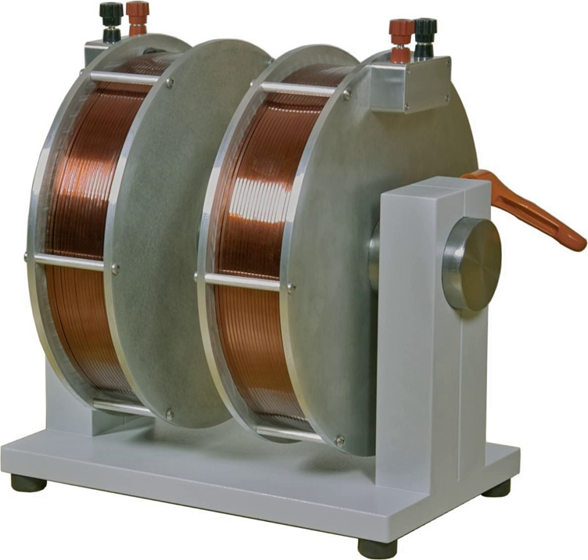The main nonlinear feature of ferromagnetic materials is that the B field saturates at a certain value, which is around 1.6 to 2 teslas (T) for most high-permeability core steels. The B field increases quickly with increasing current up to that value, but above that value the field levels off and becomes almost constant, regardless of how much current is sent through the windings. So the maximum strength of the magnetic field possible from an iron core electromagnet is limited to around 1.6 to 2 T.